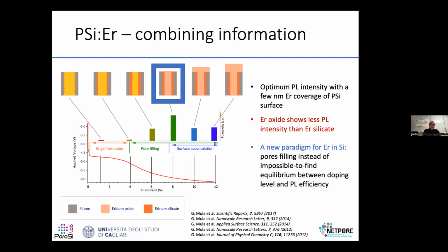So you have to change your paradigm. Instead of looking for a compromise between the loss of luminescence given by the clustering of erbium and the gain you achieve by increasing the amount of erbium, you have to look for a completely different system where you fully fill your pores. You forget about clustering because you're really filling up your pores. And then you have a matrix, which is silicon, which can be used for whatever you want in electronics, and a light emission which is stable, reliable, and intense. So the understanding of the filling process leads you to a change of paradigm for your layer, for your device, which is not possible just trying to fill the pores and seeing what the best compromise is with a low content of erbium. So this is the first example I wanted to show you.